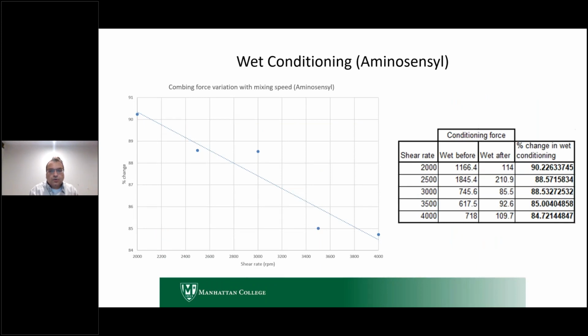And when we started to look at how that relates with the wet combing force, we saw that that was very interesting, because these differences in the shear rate also created similar differences in the combing force variation, right? That's interesting because I've always said, as a hypothesis, and it's validated here, that the yield stress is responsible for maintaining the structural integrity of the conditioner as you apply shear and you apply it on your hair and it's breaking down, right? Because the higher the yield stress, the greater the structural integrity as it comes onto the hair. So your coating on the hair is better, and as a result, you get better wet combing performance.